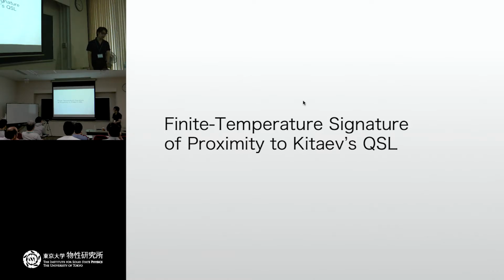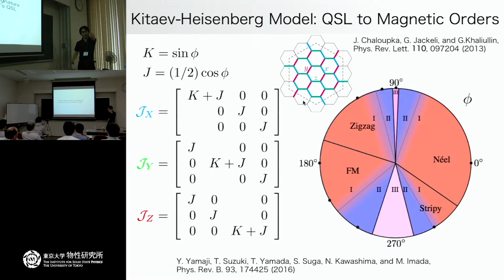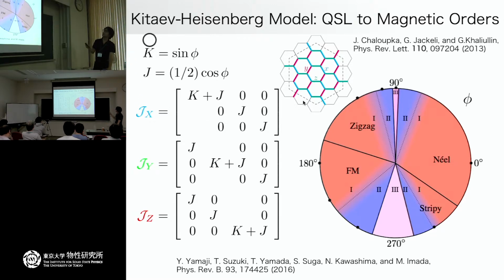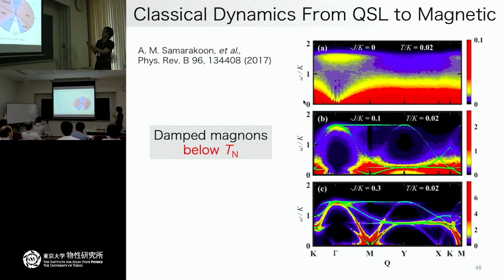Then let me apply this method to figure out the finite temperature signature of the proximity to the Kitaev spin liquid. Okay, so let me start with the global phase diagram for the Kitaev-Heisenberg model. Here, the Kitaev coupling and the Heisenberg coupling are parameterized by phi like this for the 3 different bonds. And this is a phase diagram that we try to focus on, starting from 90°, and if you enlarge this angle phi, then we go into the zigzag order phase in the ground state.